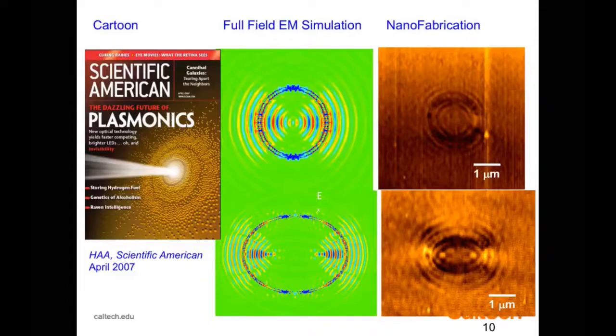We made a circular groove and an elliptical groove in an otherwise planar film of silver. Then in the simulation, we excited it and we saw these Bessel function-like bound modes of this structure. Basically, this is acting like a little resonator for surface plasmons. What we did next was to coat the surface with a photoresist material and use the plasmons to expose the photoresist. Then we took it out and made an AFM topograph of the exposed photoresist.